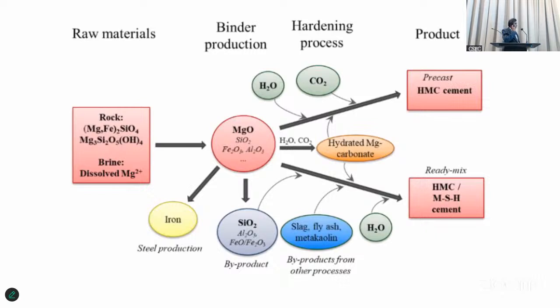This is a summary of that, where the magnesium silicates are coming from, and this can be dissolved. You don't need to heat it to that 1,500 degrees, as I mentioned, in cement production, where you get that CO2 content. In this case, it gets to the binders and the magnesium oxide is created, and the hardening process, as I mentioned, is with CO2. That will really harden. Concrete is one of the best materials invented in the world because concrete hardens.